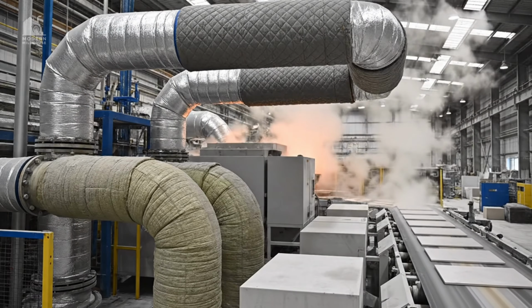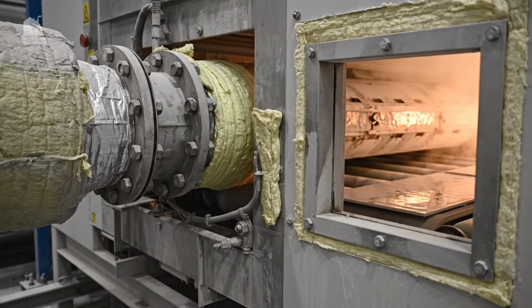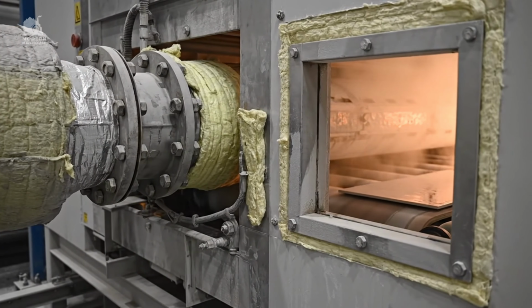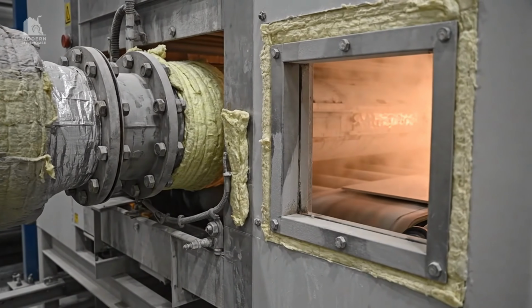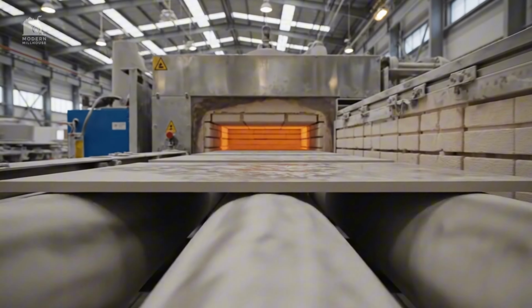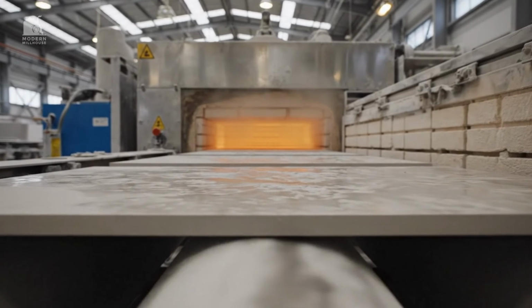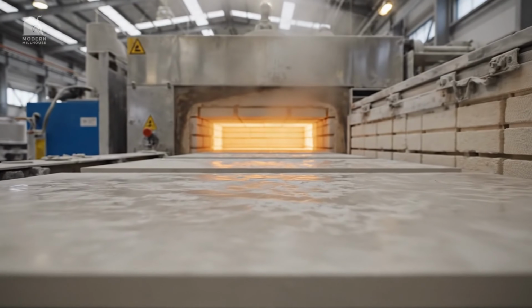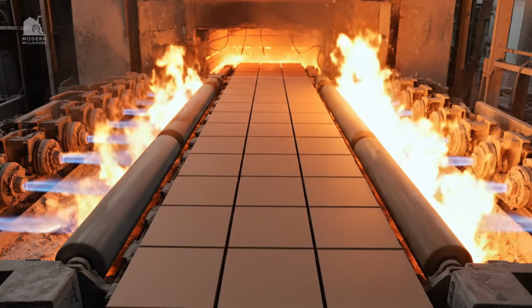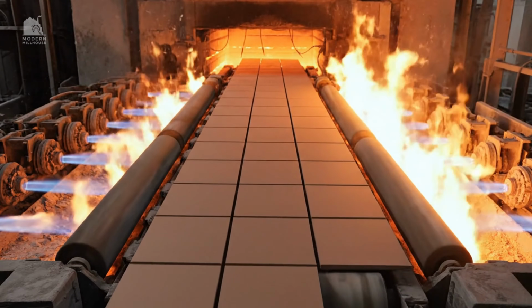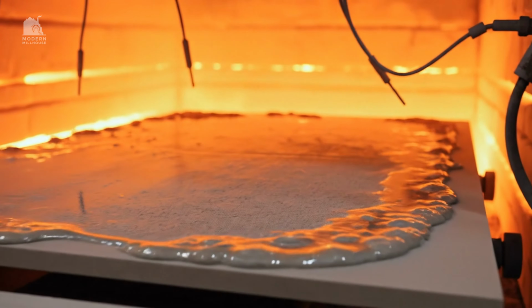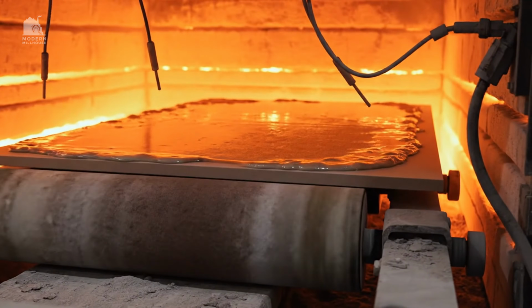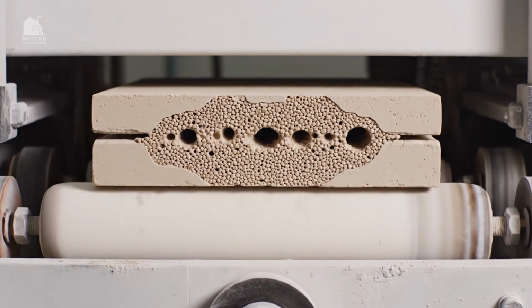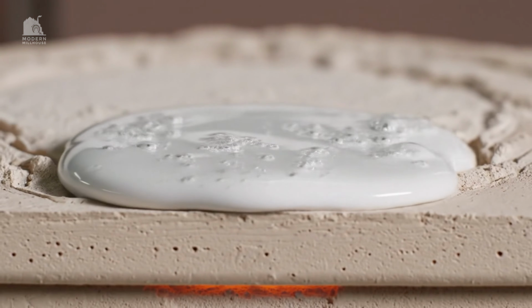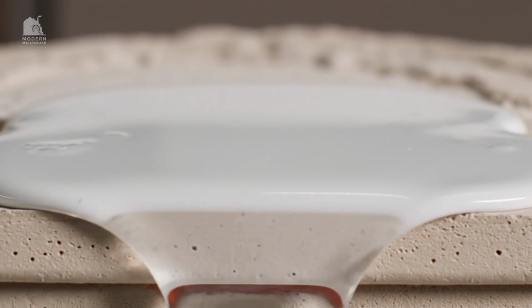Cooling is not just turning off heat. It is managing thermal gradients so glaze and body contract together. If cooling is too fast, the glaze can craze, or the tile can crack from thermal shock. Kiln control uses thermocouples, airflow tuning, and firing curves validated by production samples. Many kilns recover waste heat to preheat combustion air or warm dryers, improving energy efficiency.